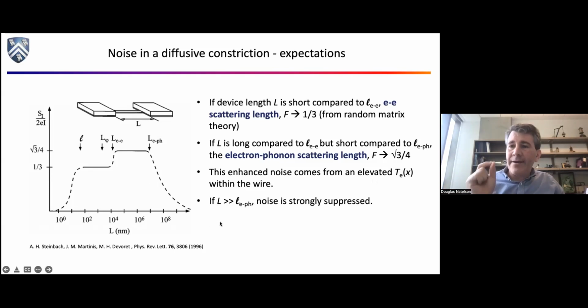This is why you don't see shot noise in the wiring in your house, in macroscopic wires. It's because you're looking at everything on length scales big compared to the electron-phonon scattering length. And at room temperature, electron-phonon scattering is also very, very important. Okay, so this is the expectation. And this is, in fact, basically what you see if you work with a normal metal like gold.